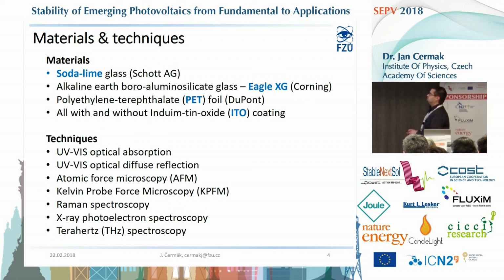We picked quite cheap soda-lime glass, a little bit more expensive boroaluminosilicate glass, which we'll call Eagle, and as a flexible substrate, we've chosen the very common PET foil, polyethylene terephthalate foil. The substrates were tested either bare, but also with the indium tin oxide coating. The samples were characterized by various techniques, and the results were compared to those obtained on the untreated, pristine samples. Such a set of techniques provided us with plenty of data. I will not present all of them. I will focus on the major ones that are the most relevant for applications.